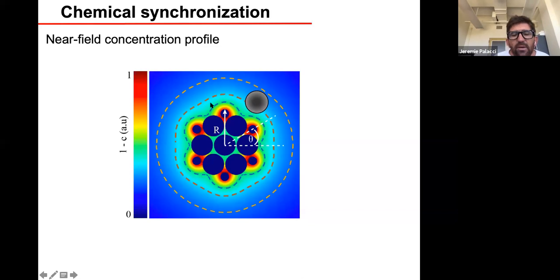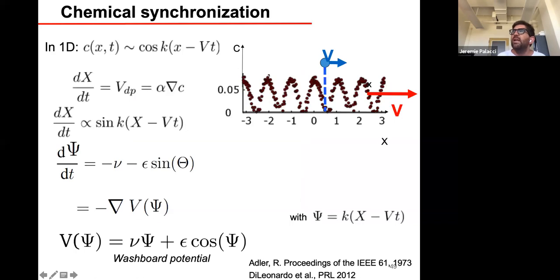And so now if we put a test particle near the microgear, and this particle is sensitive to diffusiophoresis, to make it simple, let's replace this 2D microgear by a 1D oscillation of concentration. So as a result of the rotation of the microgear, this oscillation of concentration would just travel. So you would get a traveling wave. Imagine we put a tracer particle, a test particle in this traveling wave of concentration, and this particle is exhibiting diffusiophoresis, and therefore it's moving with a mobility alpha along the gradient of the concentration. So the displacement of this particle, the position x, is going to be alpha gradient of c, with c given by a traveling wave.